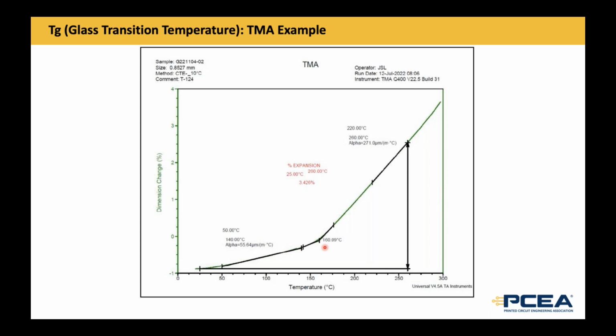But what it means is TMA is a good way to measure expansion and not such a good way to get a precise TG. So if somebody asked me, how do you measure the TG? I would say the most accurate way to measure the TG for a lot of the new materials is by DMA. There you go.